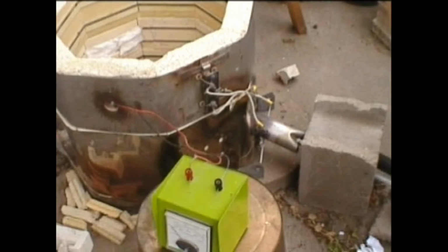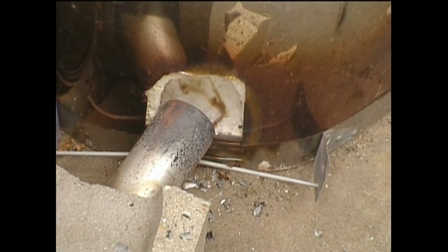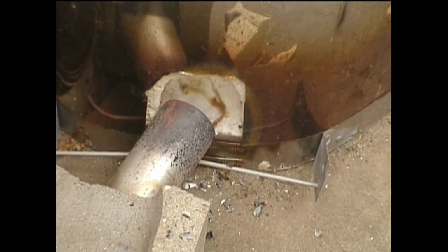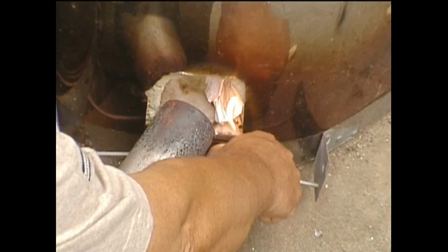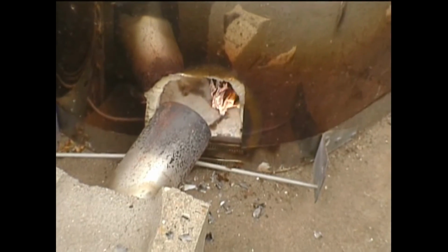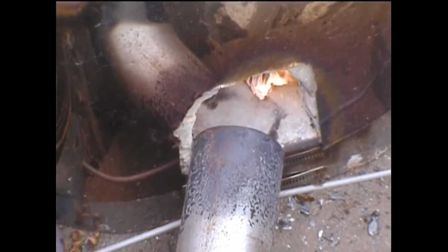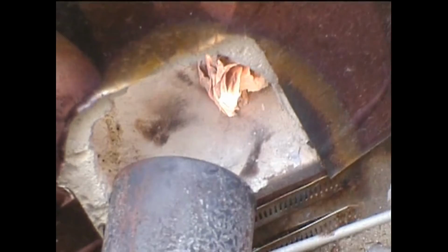As you watch the firing process, it'll become much clearer how the kiln is used and why we have built certain things the way we have. I prefer to build a small fire inside the kiln before I turn the gas on and ignite the burner. This kiln can reach 1850 degrees in about 15 to 20 minutes, depending on how heavy a load we have and how hot the kiln is when we start.